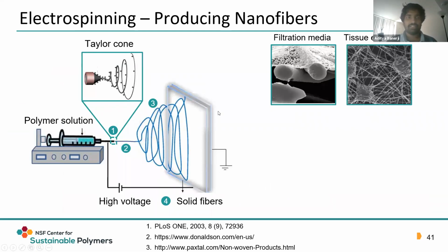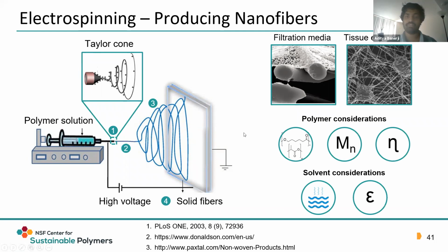In comparison, in electrospinning, as opposed to polymer melt, polymer solutions are used, which are drawn into thin fiber jets using a strong electric field in the range of about 10 to 50 kilovolts. Due to the high stretching force available, typical fiber diameters are in the range of 1 micron or even lower, into the nanometer scale.